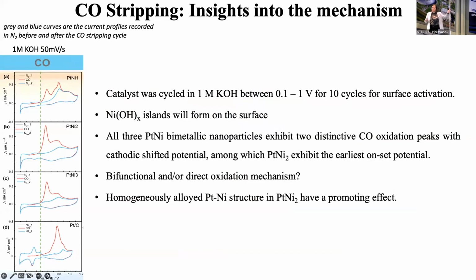Of course, if you cycle your catalyst with nickel on the surface, under this condition, you'll oxidize the nickel, and you form nickel oxyhydroxide on the surface. I always mix up the name. And so you see that all these 3 bimetallic catalysts have 2 oxidation peaks. Platinum has 1. And so that says that maybe there is this bifunctional mechanism here.